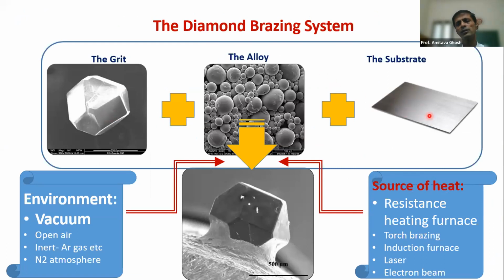Usually that's a metal substrate. It can be a cermet. Cermet is basically a composite of ceramic and metal, with a higher proportion of the ceramic. And we have an alloy which creates a bridge between the grit and the substrate. Depending on the source of the heat, you need to melt this alloy, and in the molten form, the alloy spreads on the substrate. It should react with the diamond, because unless a chemical reaction is initiated between the grit and the alloy, it is very difficult to get the right strength.